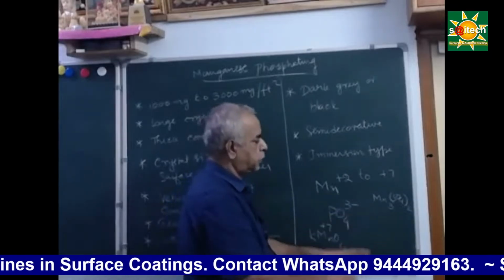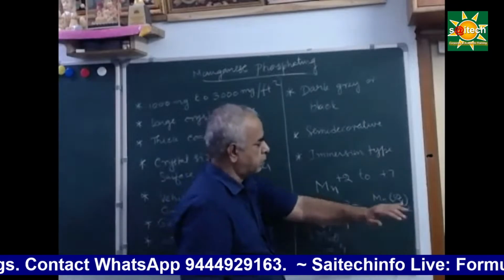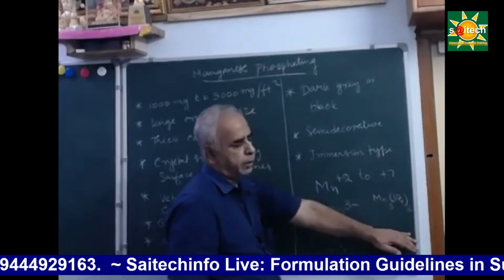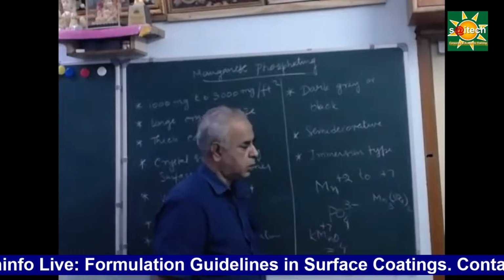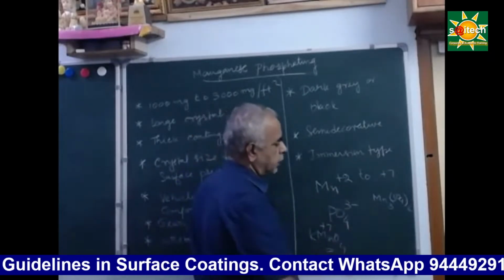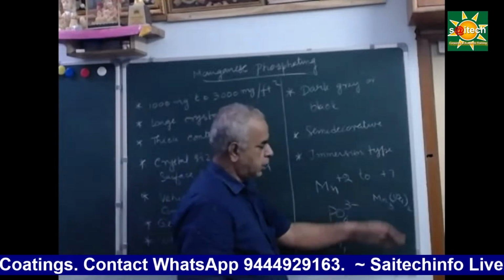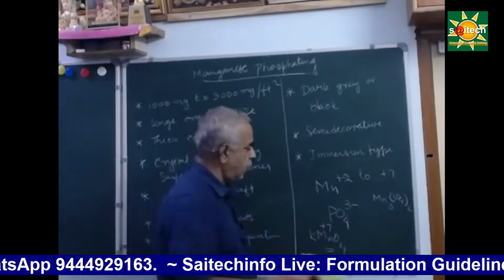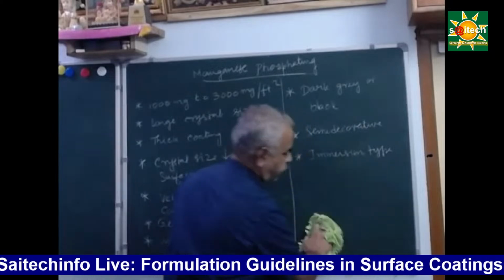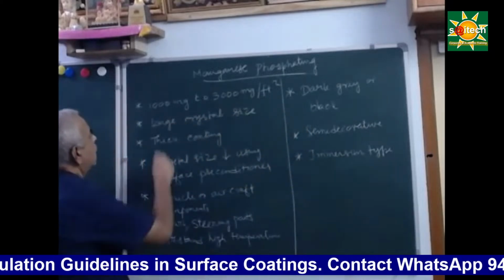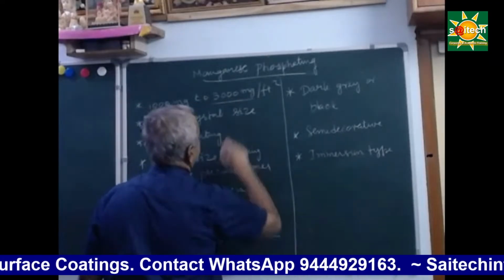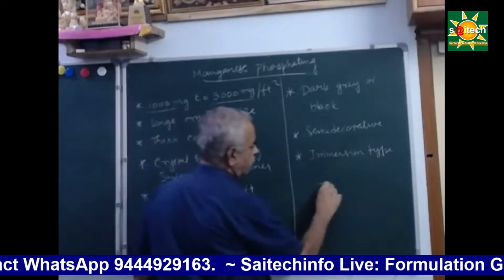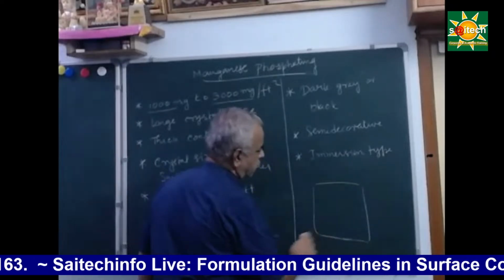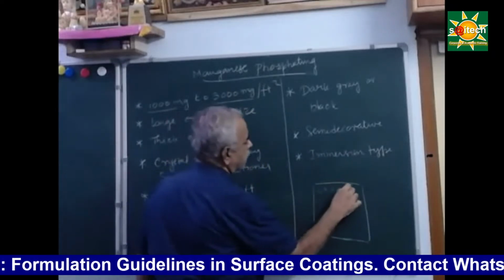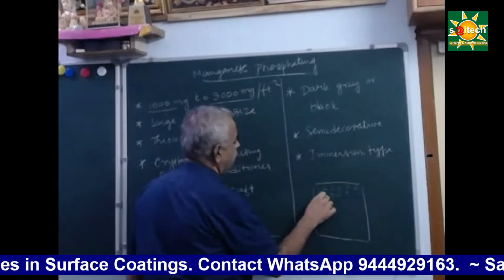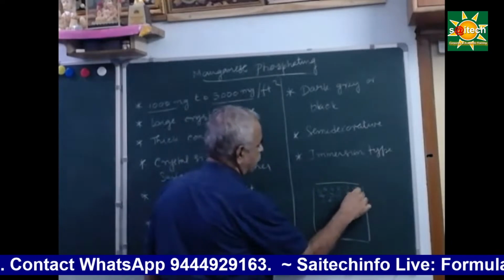It would be a combination of hydrophosphate, hypophosphate, manganese phosphate and iron phosphate. So it is a complex type of crystals. You cannot directly expect pure manganese phosphate. But the major content is manganese, and it's a heavy phosphate. Its coating weight is 1,000 milligram to 3,000 milligram per square foot. Suppose you consider a component of 1 square foot surface, it will form a porous surface, and the crystal structures will be coarser.